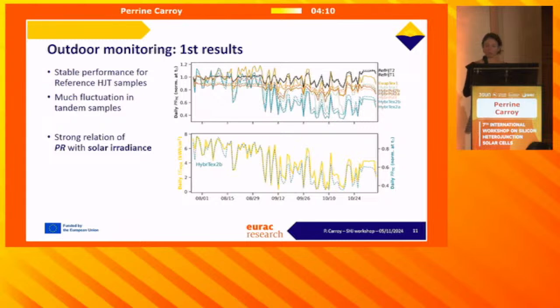So together with the 2 reference heterojunction cells that were encapsulated with exactly the same bill of materials and processes. After 3 months, we see that the references are more or less stable. For the tandem cells, we have different kinds of top cell processing and also of wafer morphology. I will not go too much into detail, but we can see that the Perovskite-SHJ-Tandem fluctuates much